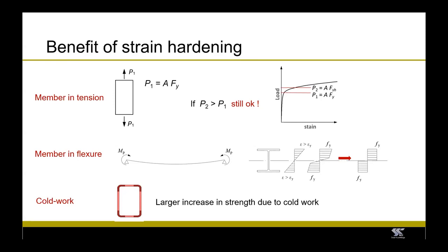And this strain hardening compensates basically for the lack of yielding in the portions that are closer to the neutral axis. Now, bear in mind that due to the gradual loss of stiffness of stainless steel, the portion of the cross-section that doesn't reach the yield strength is larger than for a carbon steel beam. So in this case, strain hardening is very beneficial for stainless steel.